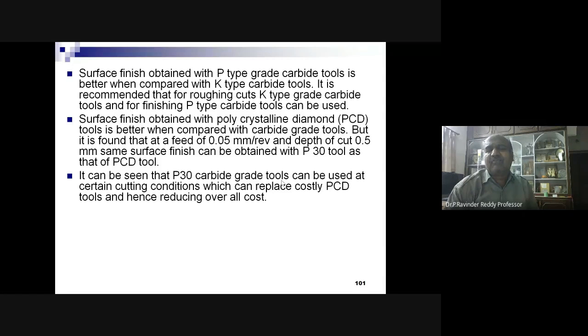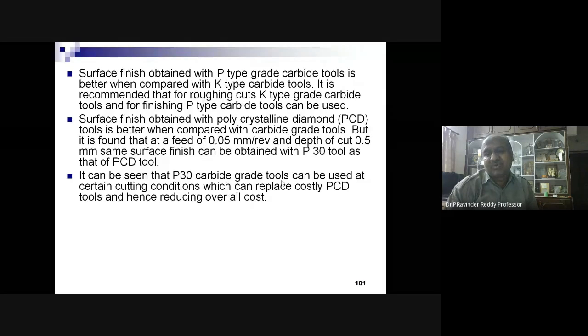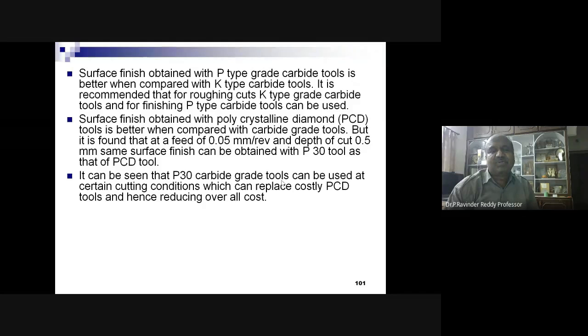at a feed of 0.05 mm per revolution and a depth of cut of 0.5 mm, the same surface finish can be obtained with a P30 tool as that of a PCD tool. It can be seen that P30 carbide grade tools can be used at certain cutting conditions, which can replace costly PCD tools and hence reduce overall cost.